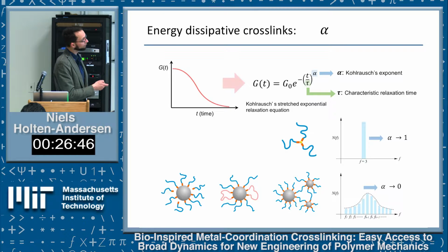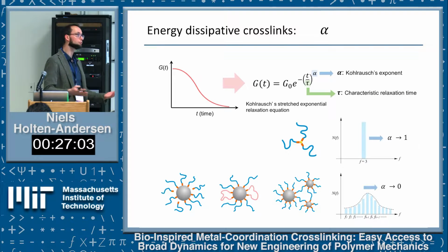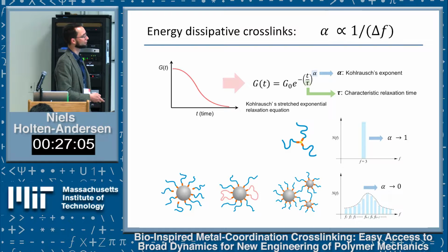This type of math allows you to measure a parameter we call alpha. If alpha is close to 1, it means you have a very narrow distribution and it won't be a very tough material. If alpha is very close to 0, you have a much broader distribution and you're going to get a much tougher material.